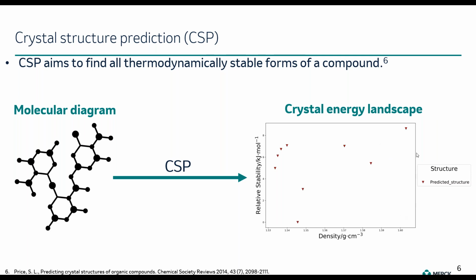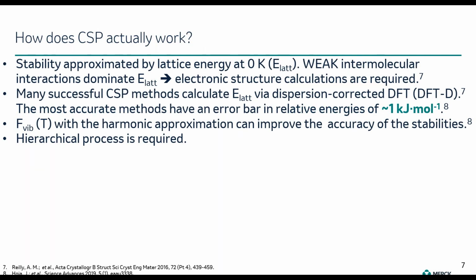So each of these points in this landscape is a predicted structure. The lowest energy one is predicted to be the most stable, and the alternative ones are predicted to be metastable relative to the global minimum in thermodynamic energy. How does CSP actually work in practice? In most cases, the thermodynamic stability is approximated by lattice energy at 0 Kelvin. Lattice energy is the energy required to separate the molecules in a crystal to an infinite distance in their lowest energy conformations.